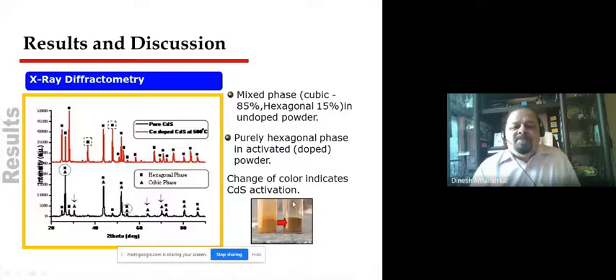The first test is visual change in color. The material in the pure form, cadmium sulfide in the pure form, is yellow in color, which becomes rather brownish or reddish in color after the activation process. Of course, there is a change in crystal structure also. The undoped cadmium sulfide, in my case at least, we can find it is a cubic dominated mixed phase, cubic 85%, hexagonal 15%, while after doping, it becomes perfectly hexagonal structure.